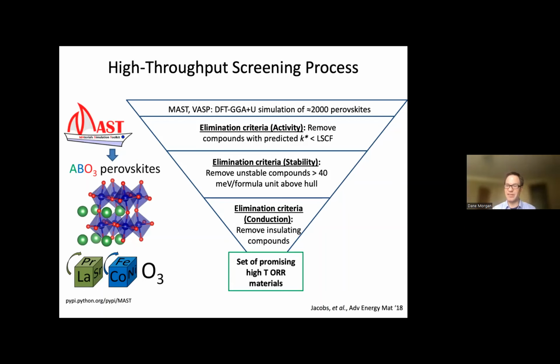And then it better be stable. So we took a cutoff in stability that was 40 meV per formula unit. That's basically the error bars of the DFT. So we said it should be stable within error bars of DFT. And we said no insulators, because no one's going to want to make an electrode out of an insulator. And then we basically used those to weed out everything that wasn't promising. And what we're left with are our most promising materials.